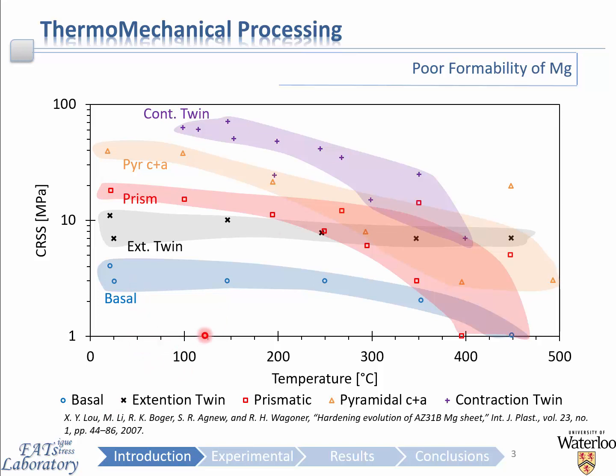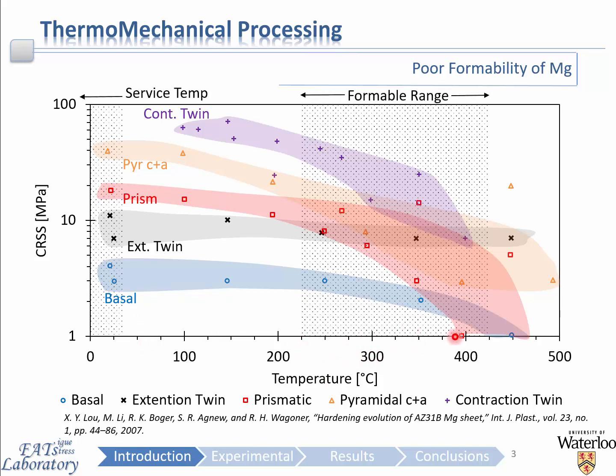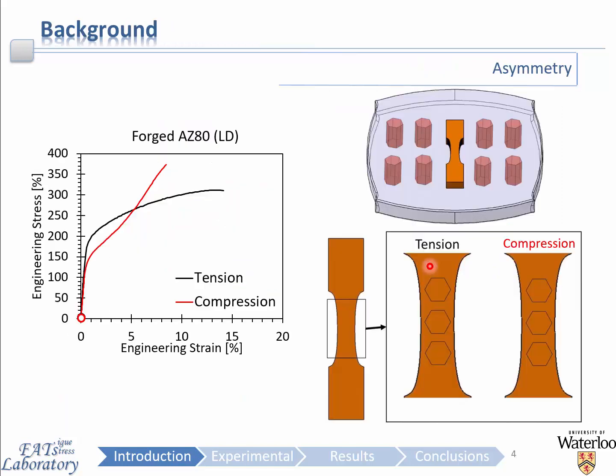However, at elevated temperatures in the range of 225 to 425 degrees Celsius, the critical resolve shear stress of the other modes decreases dramatically, improving the ability to plastically deform and thus the formability of the material. So what this means is that to successfully process magnesium and achieve large strain via forging, it must be done at this elevated temperature regime. This introduction of temperature into the processing equation complicates controlling the resulting microstructure quite a bit, as well as the fatigue behavior, as the process is now highly thermomechanical.